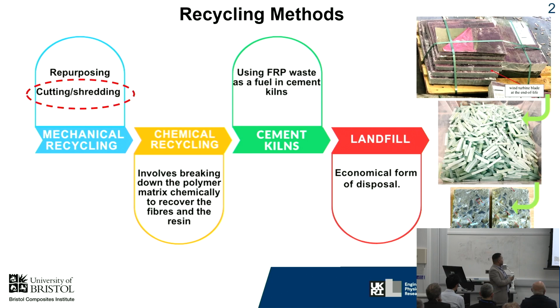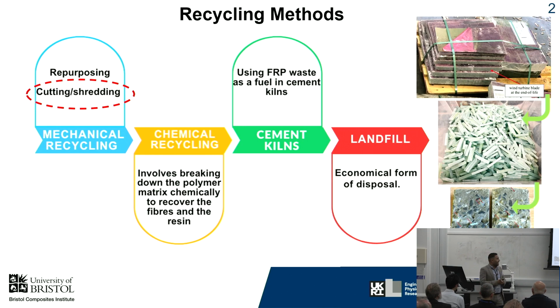In terms of my PhD project, it's about cutting and shredding. So my PhD will partially participate in the recycling chain of wind turbine blade materials, mainly the GFRP. As you can see on the left-hand side, the materials were provided by Vestas, then cut to a certain geometry with a 50 mm length and 8.3 aspect ratio, and then mixed with concrete at different percentages, 2.5%, 5% and 10%, to study the effect of those GFRPs on the concrete's mechanical properties.